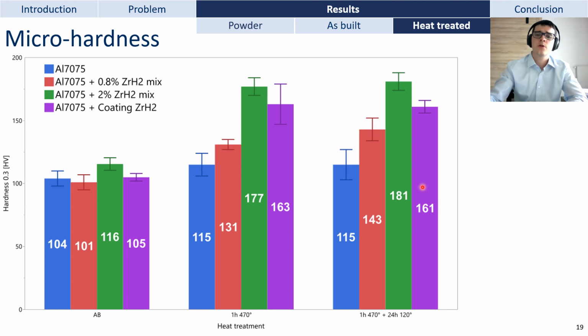We reach a maximum of 181 Vickers for the aluminum 7075 with high zirconium hydride content, but there is still room for improvement for that value since the aging treatment seems to have no effect at all. So we are currently still optimizing the heat treatment.